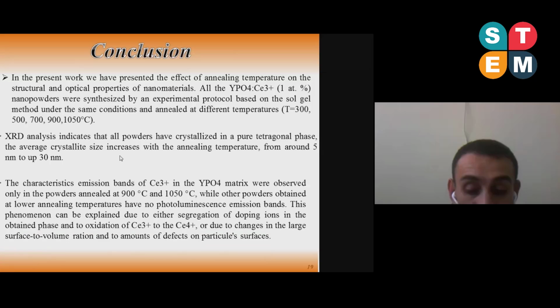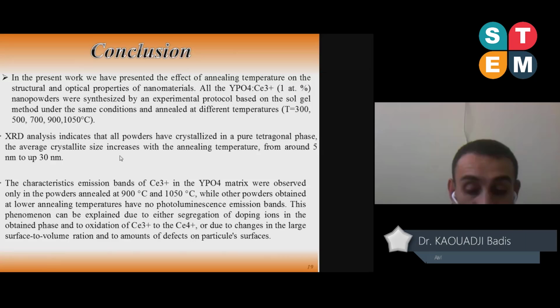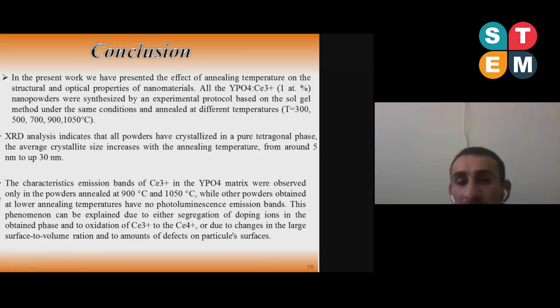The characteristic emission bands of cerium 3+ in the yttrium orthophosphate matrix were observed only in the powders annealed at 900 degrees and 1050 degrees Celsius, while other powders obtained at lower annealing temperatures have no photoluminescence emission bands. This phenomenon can be explained either by segregation of doping ions in the obtained phase and oxidation of trivalent cerium ion to the tetravalent cerium ion, or by the change in the large surface to volume ratio and the amount of defects on the particle surface.